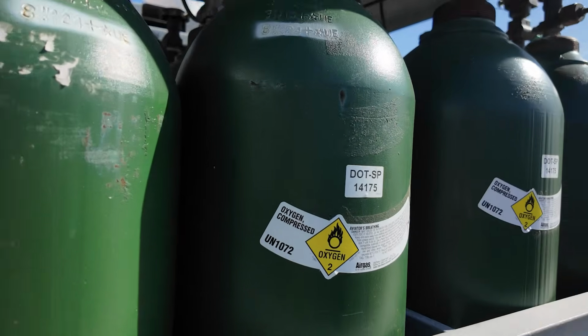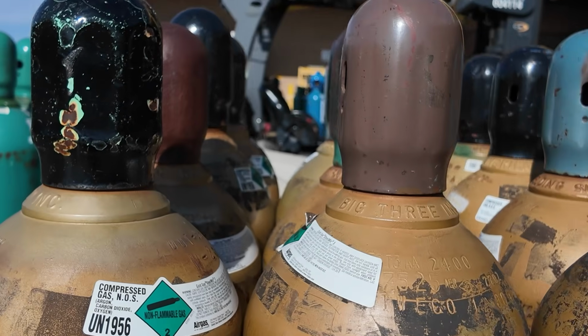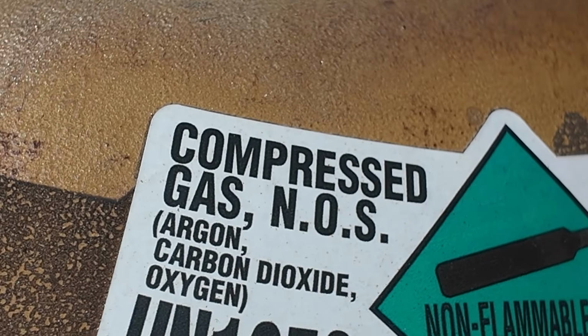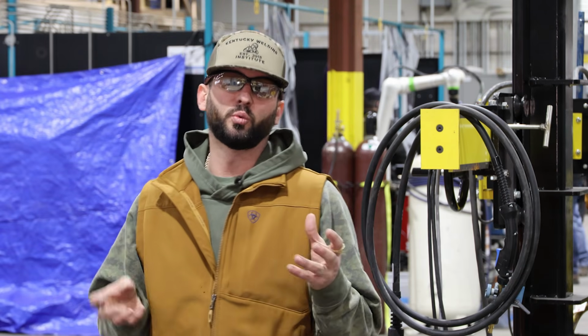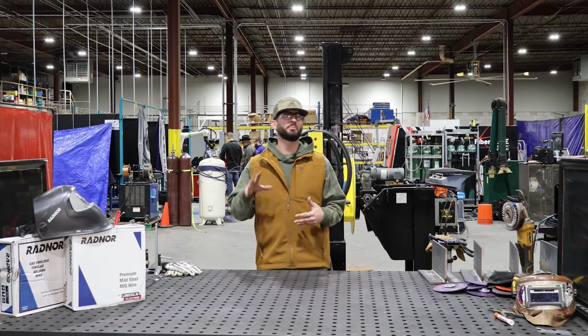Oxygen is not a gas that we talk a whole lot about, but it does mix into a lot of these different mixtures, and it has a whole lot of benefits to it. Now, be forewarned, we're only going to mix oxygen in very small amounts in order to have some good things come with it. When we do, it's going to decrease the surface tension of a weld puddle. It's going to make things a little bit more fluid, allowing for a lot faster travel speeds, which all in all sounds really nice, but add a little bit too much oxygen, you can really make a weld really brittle and lose all of its strength.